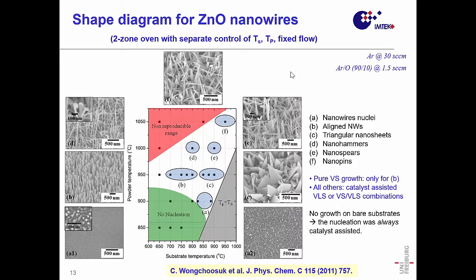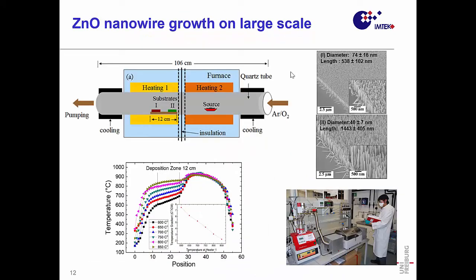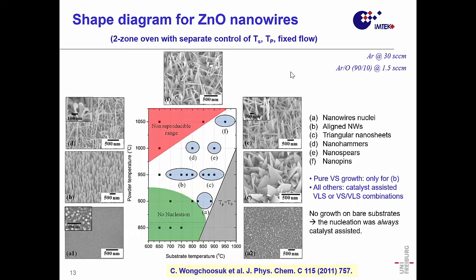Okay. The next point you have to decide, if you go back to this furnace, is at what temperature you evaporate your powder, because that gives you the amount of powder and how much gas comes out. In addition, there is the temperature of your substrate. All of these parameters influence what you are growing, and you want only the one in number B, that means the nanowires, but not all the other structures which you see if you do not have good control of the temperature, because those you cannot really use for devices.